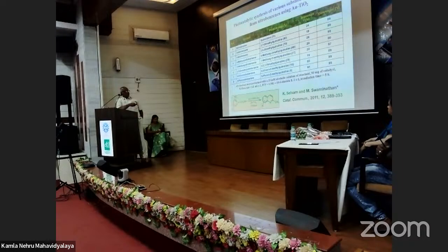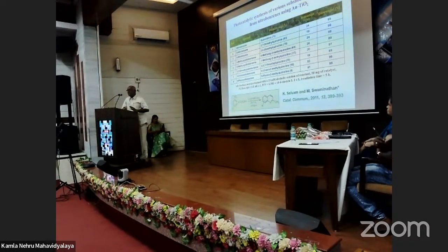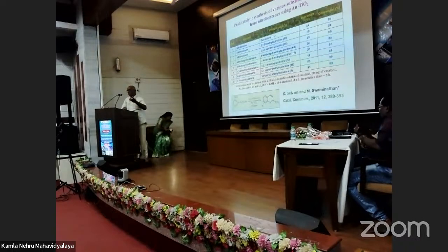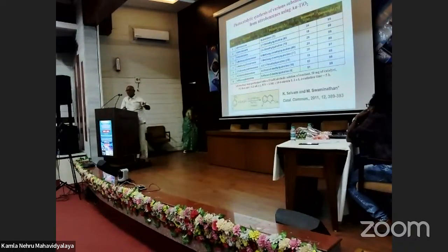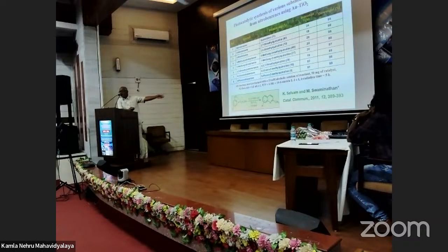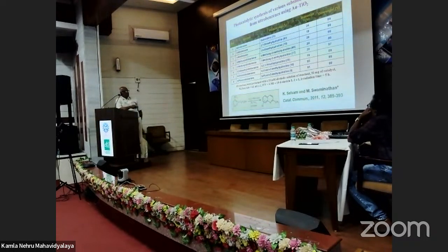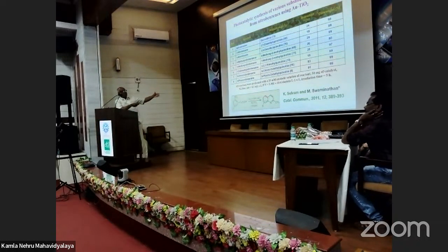Another one is the redox reaction which I was telling you about, where it can be used as a redox catalyst both for oxidation as well as for reduction. So we took nitrobenzene and alcohol. Nitrobenzene is reduced to aniline and alcohol is oxidized to aldehyde, and they combine together forming the quinoline. So this was actually a combined redox reaction, a redox catalyst in multi-step synthesis, but we are performing all three in only one step. You can see that this was very good, and he took nitrobenzene and substituted nitrobenzenes, and we are able to get very good conversion efficiency.